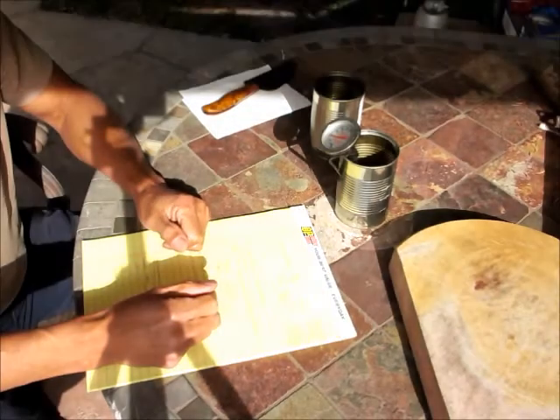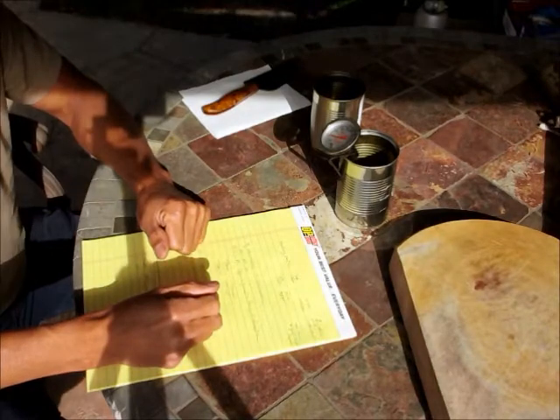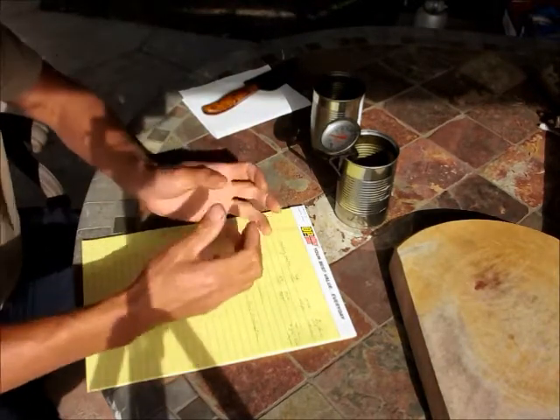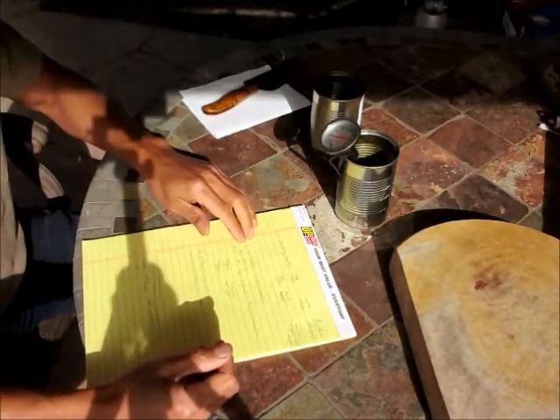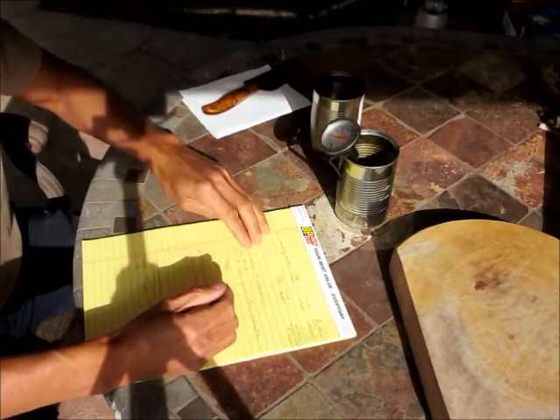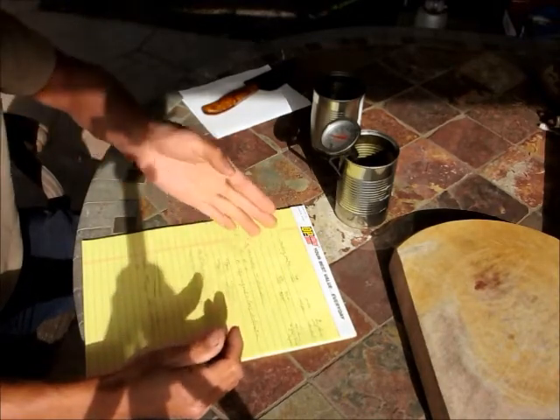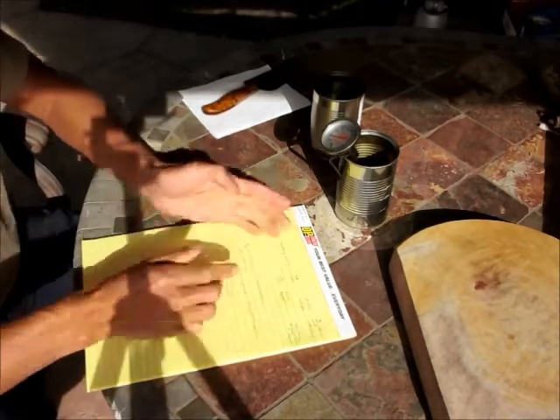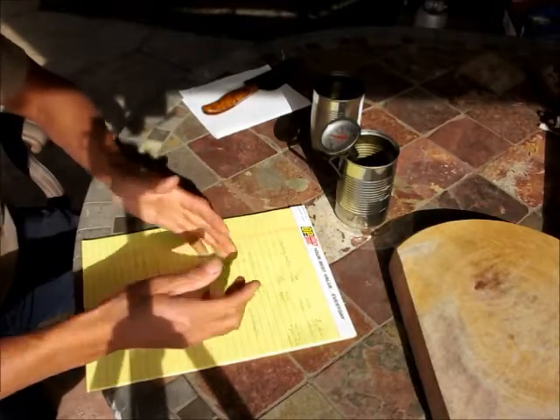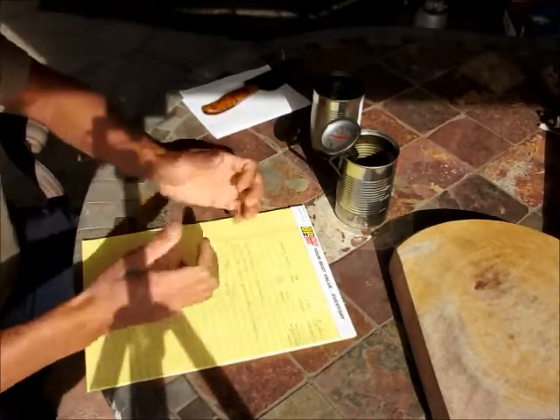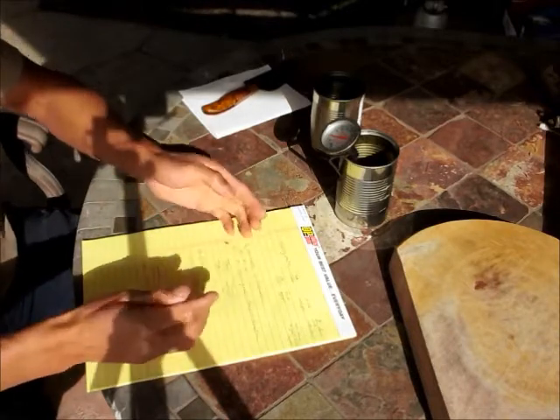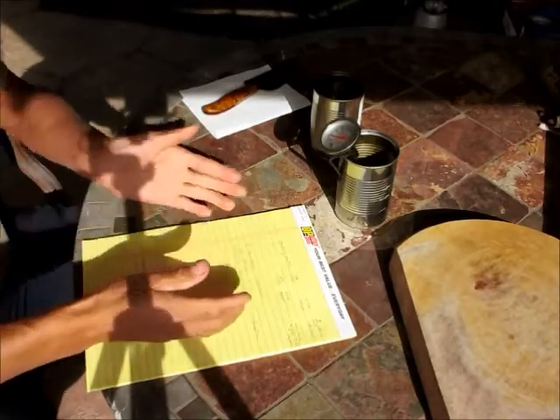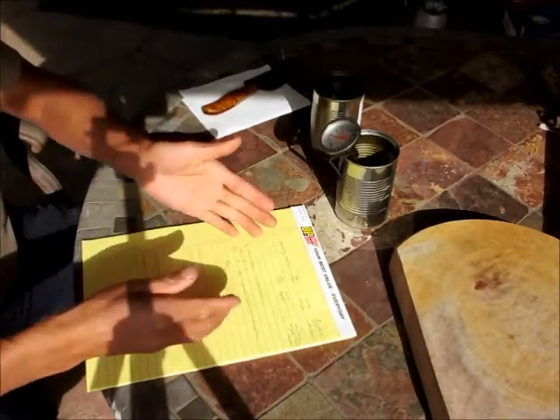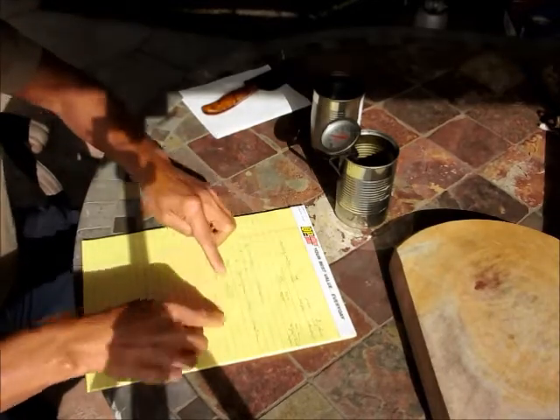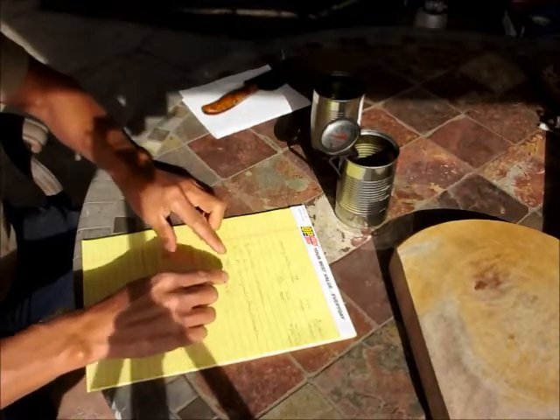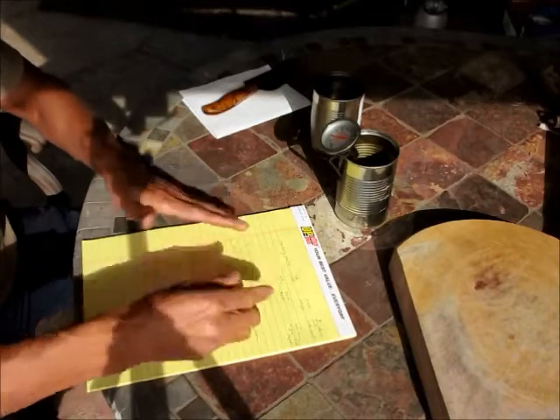One, you can heat it up a little bit, the whole system. In this case, when you heat up, you have thermal expansion, and so suddenly you release, you add a little room. So the retained austenite now has to decide, okay, do we have enough energy to shift to the martensite shape? Or is there enough to activate it to totally break it down, instead of the BCT structure, into a more triangular, pyramid shape of cementite? So that is the thing about it.